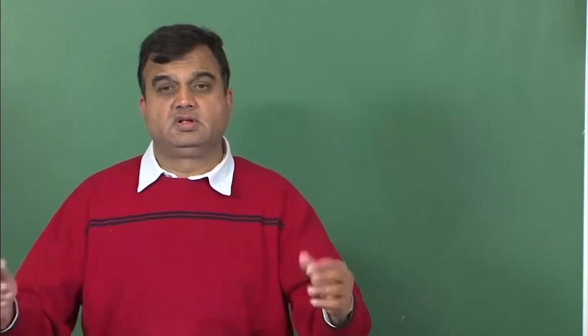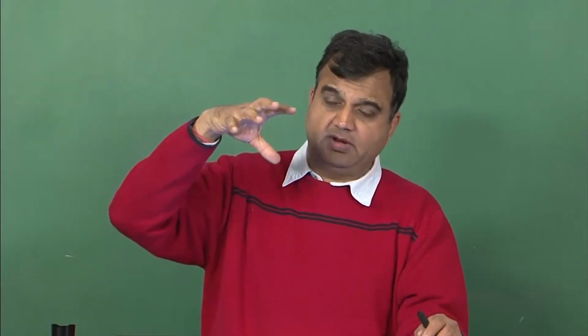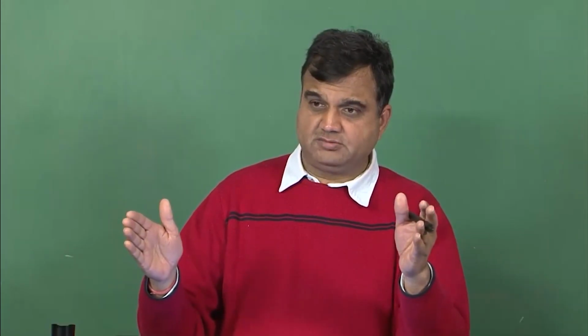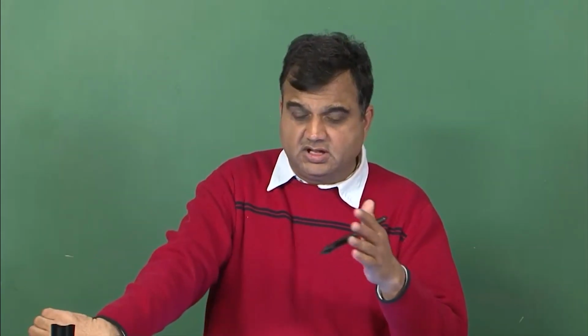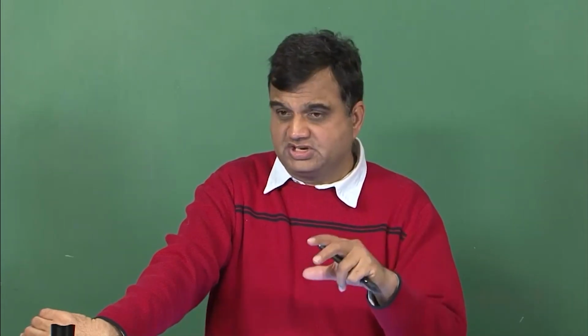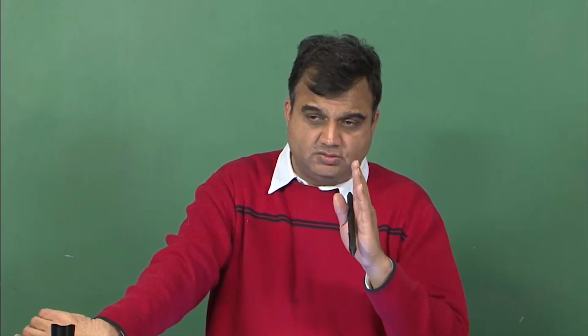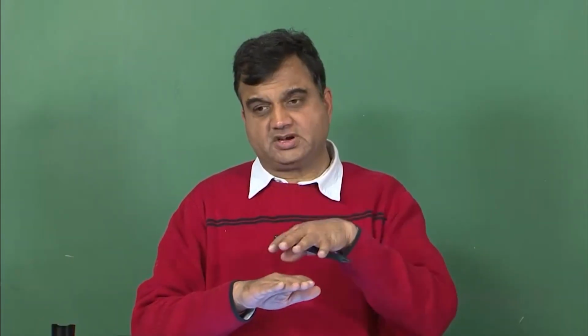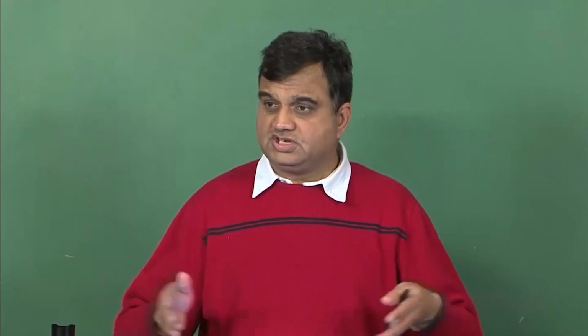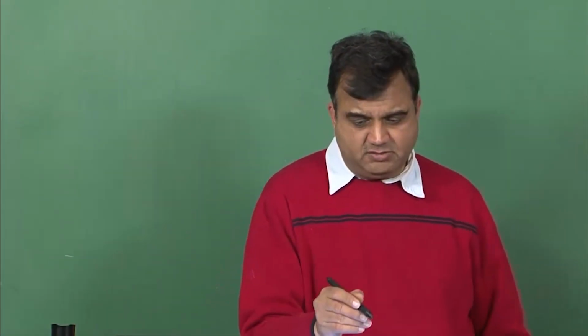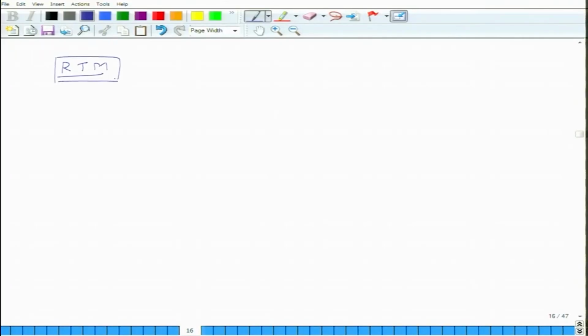So, a limitation of the vacuum bag molding or bag molding processes is that the fibers, when you apply a lot of pressure, tend to dislodge from their original position, and there is a chance that the orientation of the fibers in the system, especially if you use external pressure, may not be same as what you intended, because as you apply external pressure, the fluid flows at a higher velocity with high pressure and it tends to change the orientation of the fibers. So, RTM is one method which helps us produce good quality composites in a way that the fibers do not get overly dislodged from their original position.